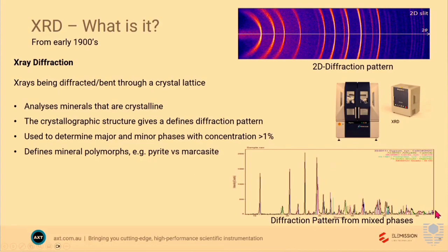But in the real world of minerals, it's very rare that you have just one mineral phase. You have multiple mineral phases. And so you end up with a diffraction pattern from all the different mineral phases. And so XRD started off as a qualitative measurement. It will tell you what's there, and then came Rietveld analysis, which sort of deconvolutes that mixed spectra, and then you can quantitatively, theoretically, work out what minerals are present.